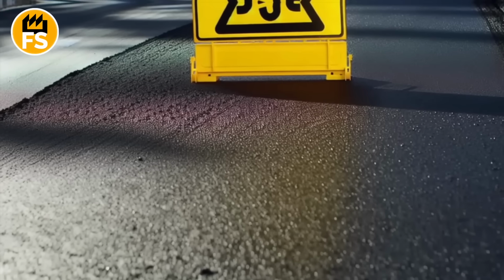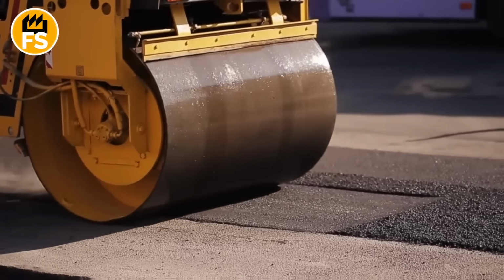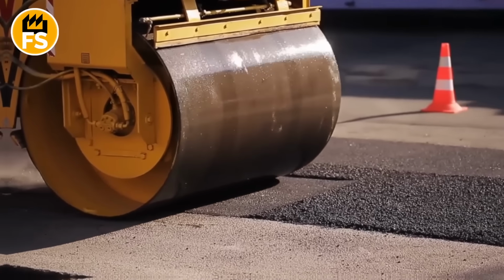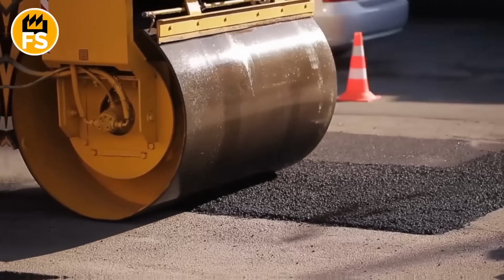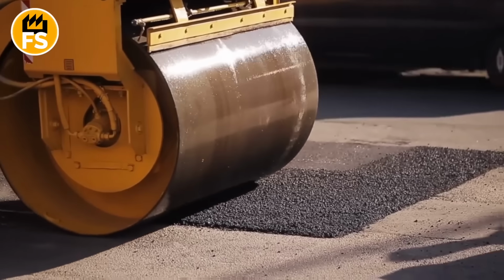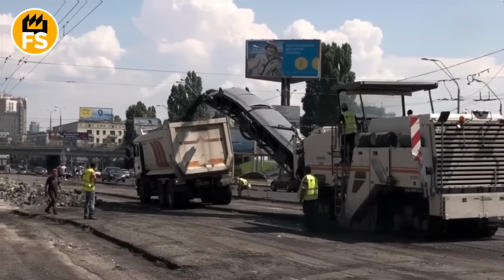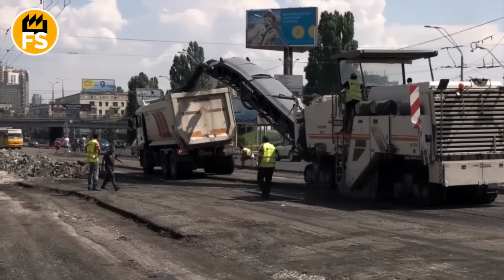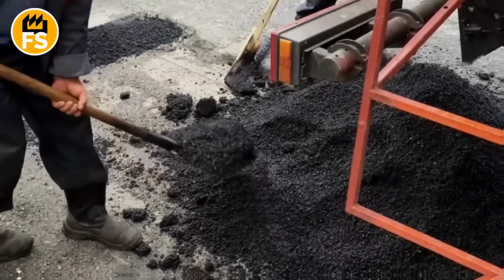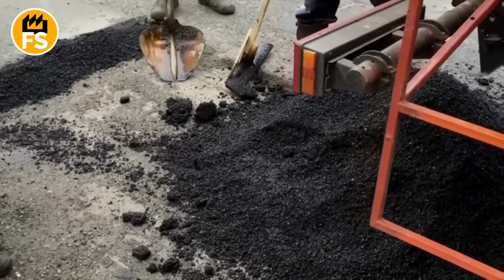Meanwhile, road surface service life increased on average from 7 to 10 years to 12 to 15 years before the first major repair. This significantly reduces overall infrastructure costs. Although initial polymer asphalt installation costs are higher by approximately 15 to 20%, long-term savings can reach 50% due to reduced repair needs.